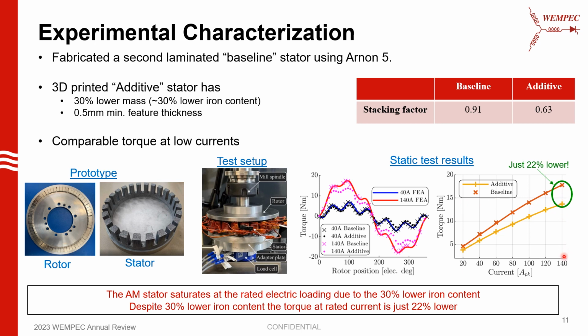At the rated current of 140 amps, it can be seen that the torque on the additive stator is just 22% lower, although we had expected it to be 30% or more. This shows that not all the iron that was removed in the additive stator actually contributed to useful torque.